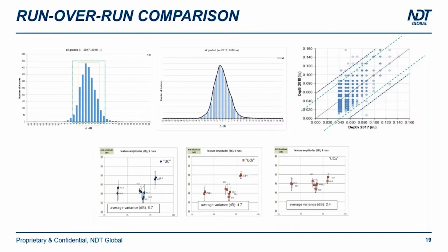So if we go to the right side to the Unity plot, we will see that we have 2018 on the y-axis and 2017 on the x-axis. In this case, the green lines delimit the tool tolerance as designed, 40 mils. And the blue lines delimit the statistical tolerance. So even not considering the statistical tolerance, everything is behaving as within 40 mils as expected and as designed.